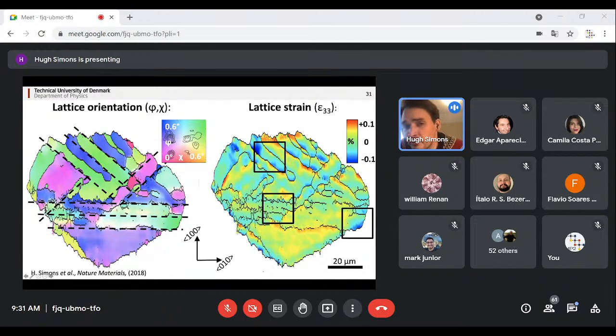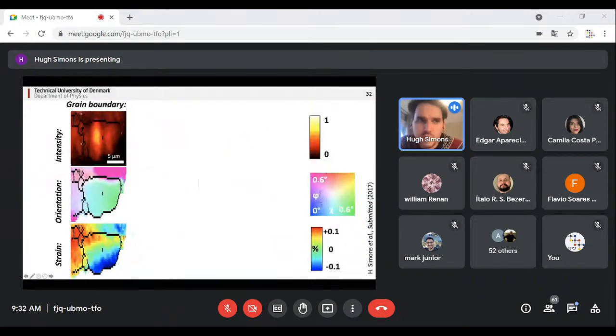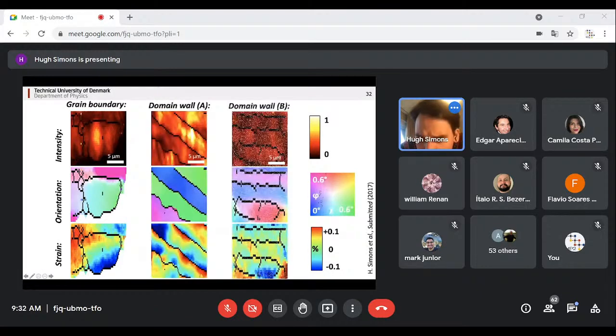And you can also see features you might be interested in. So for example, these domain walls at 45 degrees here, these other domain walls here, and also grain boundaries. But if you look a little bit closer at how the lattice orientation and the strain are distributed around these defects, I'll just show you some zoom-ins of exactly these types of features. You can see something very important here, which is that the gradient of the strain extends right the way through here. And this is on the scale of 5 to 10 micrometers. The same thing happens with domain walls. The strain fields generated by the domain walls really extend the full extent of the domains here.